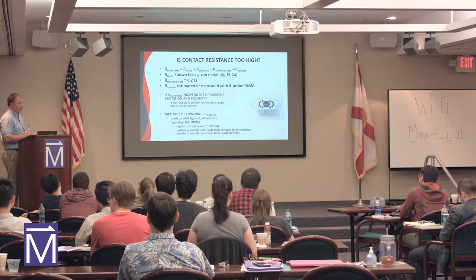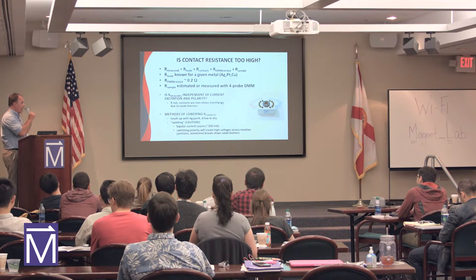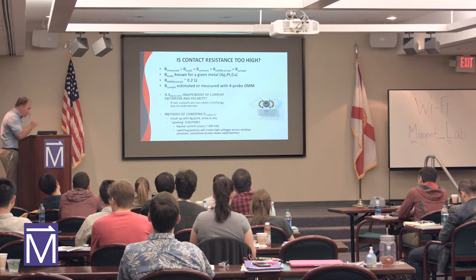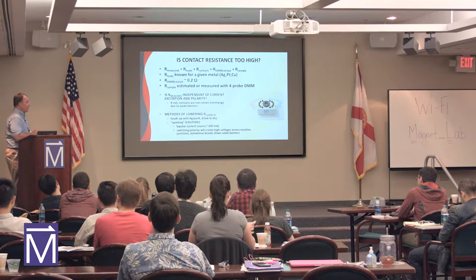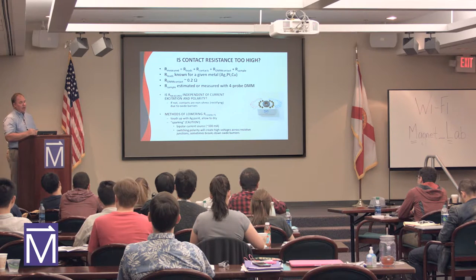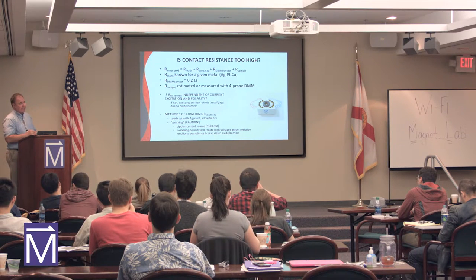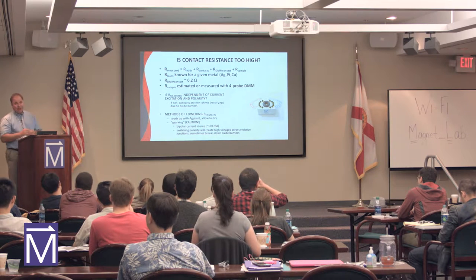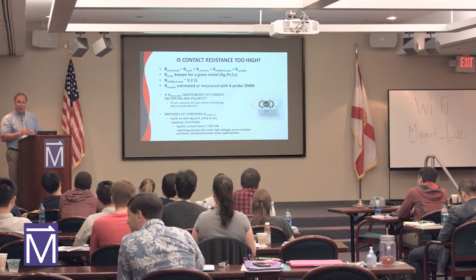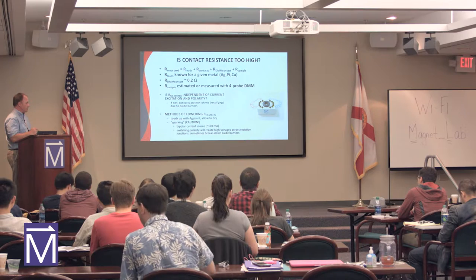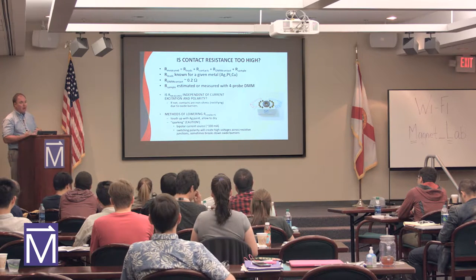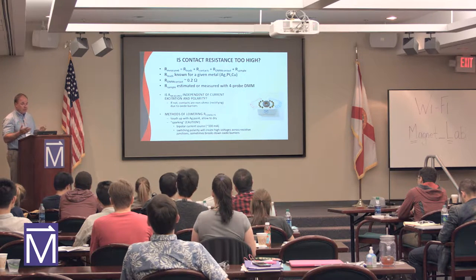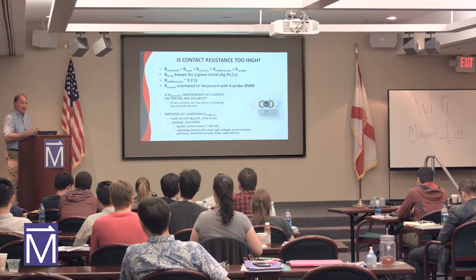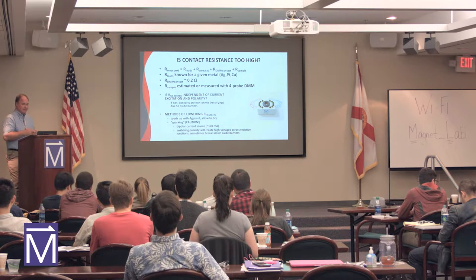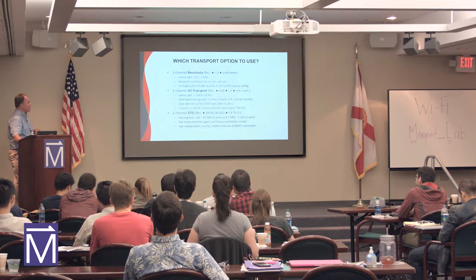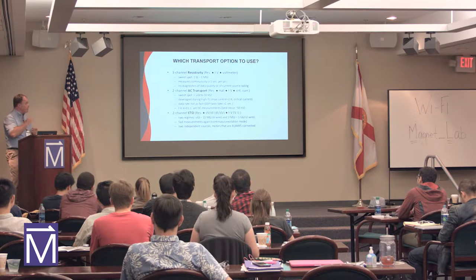So how do you reduce the contact resistance? Touch it up with some silver paste and let that dry. Sometimes if you have an oxide barrier, you can remove it by putting a little spark across the sample. You just have to know the trick to it. Sometimes you don't want to do that because it'll destroy the sample. But you have to think about your connections from your sample to the instrument. There are lots of little tricks and tips for that one.